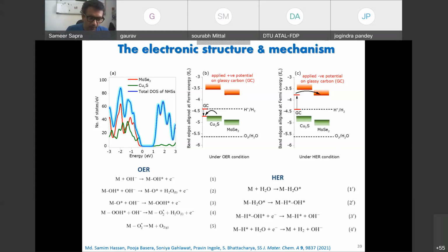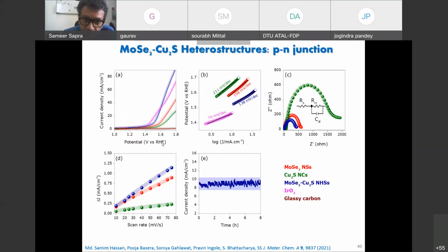But OER happens better under alkaline conditions, and HER, H plus going to H2, would be better under acidic conditions, but it does happen under alkaline conditions, and here's the mechanism over there. Well, I don't need to describe the mechanism, but later if you have some questions, we can come to that. So looking at the OER reaction, look at this one. The pink purple one is iridium oxide, which is the industry standard. The blue one is molybdenum selenide, cuprous sulfide. And you see that our material is pretty much as good as IrO2, not too bad, except that you need a slightly higher voltage. Again, iridium is very, very expensive.